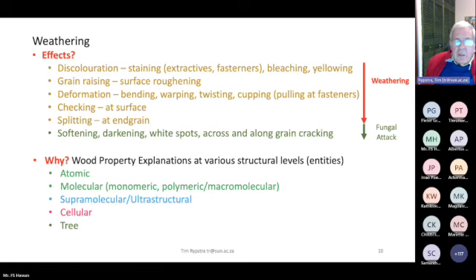So these phenomena are associated with weathering, and then if this carries on, there's softening, darkening, white spots are formed, and across and along grain cracking, which is typically associated with fungal attack, which sets in when moisture content levels are normally above 20% moisture content.